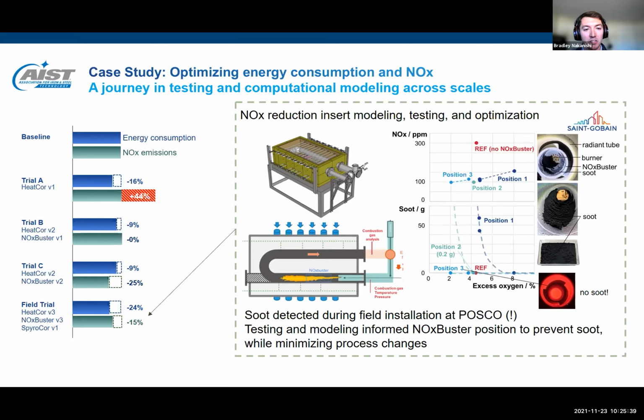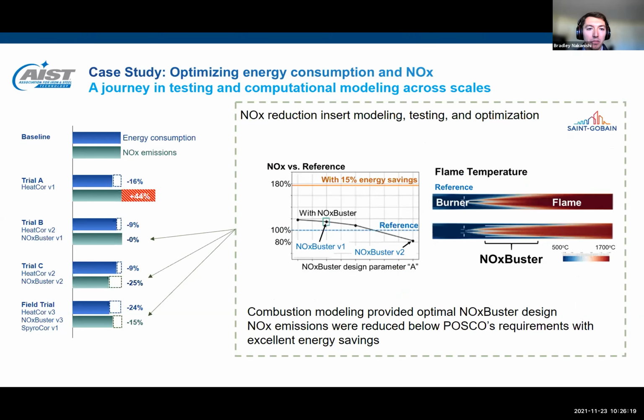Long story short, Saint-Gobain's R&D teams reproduced POSCO's conditions using our own pilot furnace based in Paris and conducted a series of tests and simulations to determine the root cause and develop a viable solution. Together, POSCO and Saint-Gobain learned that managing NOx buster position during the installation process is very important to prevent soot formation, and we obtained a good solution that ultimately simplified the installation process and had little to no impact on furnace operations.